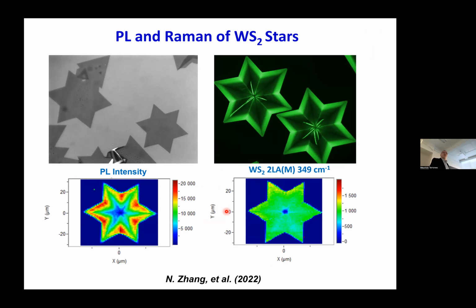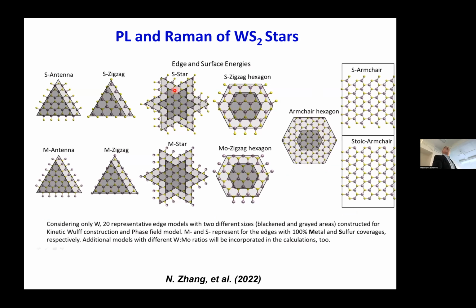And then these are monolayers. And again, here, in this tungsten disulfide, you have very sharp photoluminescence. Here you have a very bright edge. So these are twin boundaries, and you have darker here, which is basically more vacancies that we have. But these stars have been made. And in here, we play a little bit with the tungsten concentration, and a little bit of the moly concentration. So we're playing with different parameters, but in principle, we can control the growth of this. I mean, we're working now on this and trying to understand the growth.